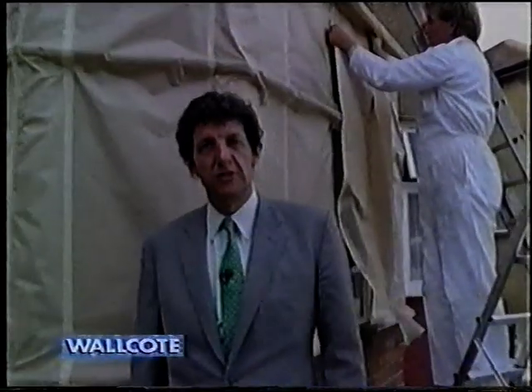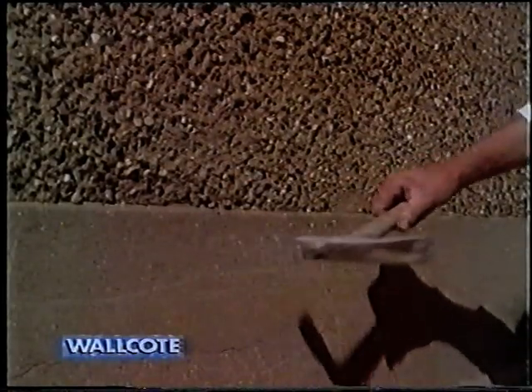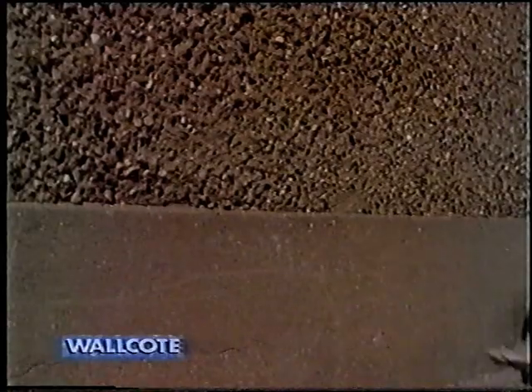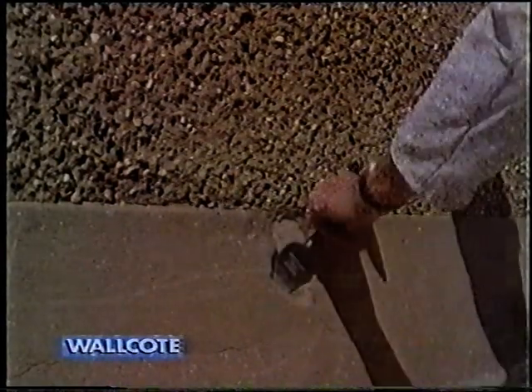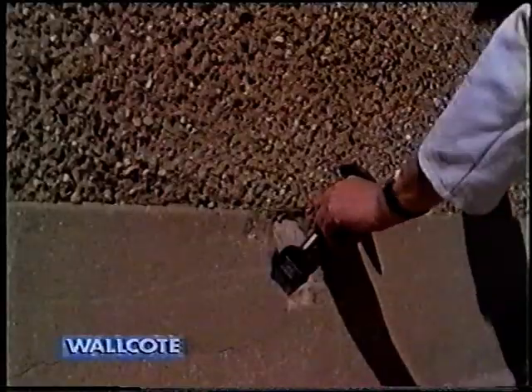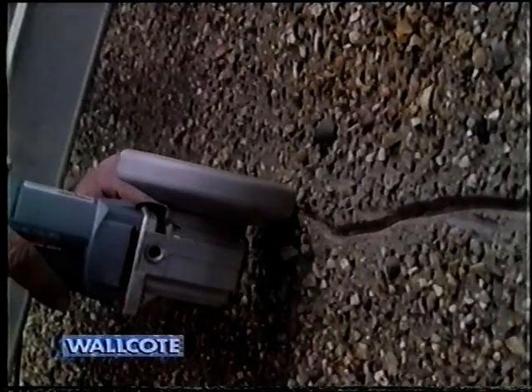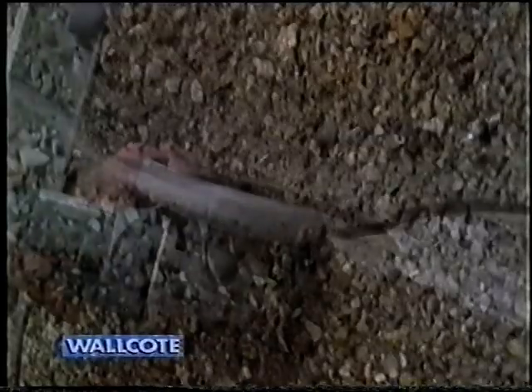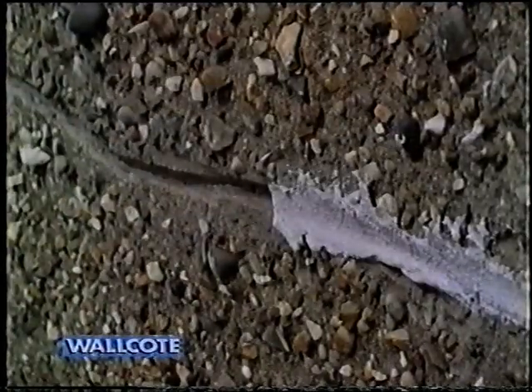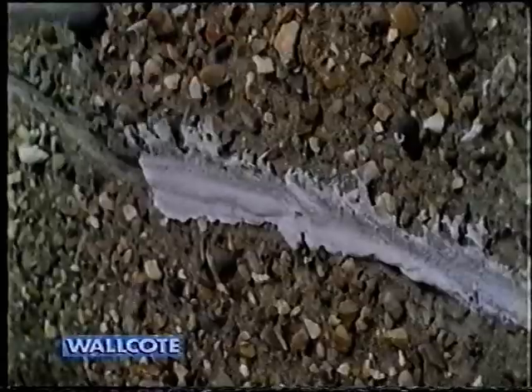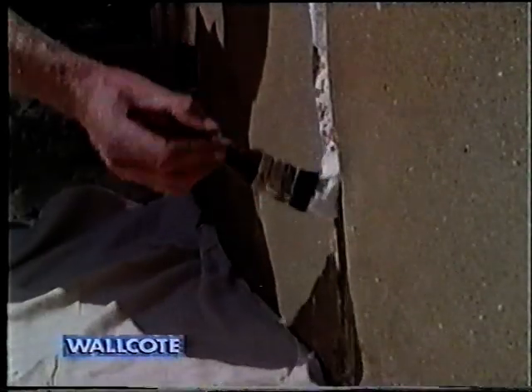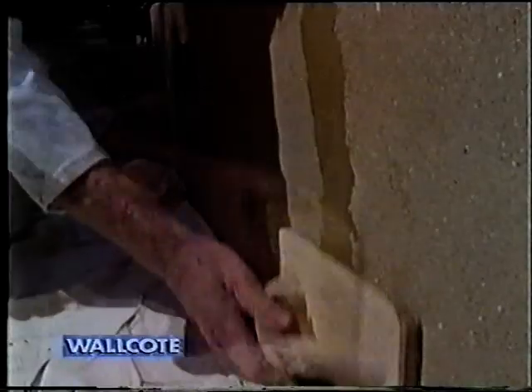The next stage is the most critical. All the faults which were noted on the original survey have to be found and corrected. Firstly, render and pebble dash are hammer tested to locate hollow areas. These are completely removed, cut back to sound surfaces. Small cracks in otherwise sound areas are cut out and filled with epoxy resin. Large cracks are treated with special bonding primers and filled with a sand and cement mixture. This is then finished to match the surrounding surfaces.